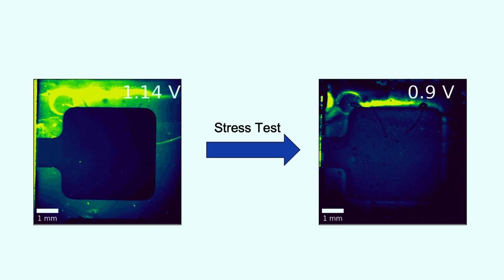And we can kind of go in with our X-ray, for example, and ask, what is it about the atomic structure of this point that made it degrade more than this point? One key finding from our work is that we were able to produce a passivation layer on top of this material to enable it to have a much longer lifetime and a much more durable solar cell.